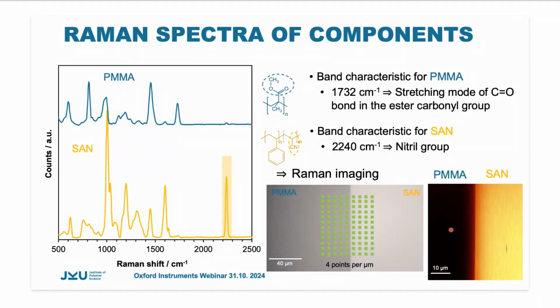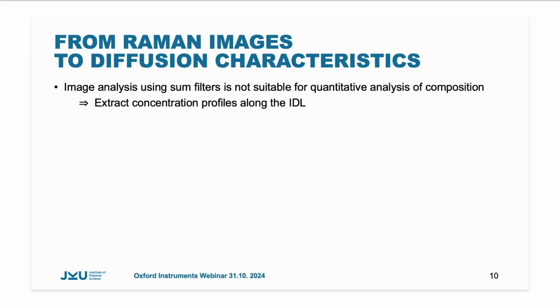What's obvious here is that we have a very nice sharp boundary between the polymers, and when you look a little bit more into details of the film, you see that there's a blurring of the color at the interface, indicating that we have a mixture here of the polymers in this region. Now the question is, how can we learn more from the Raman imaging about diffusion characteristics?